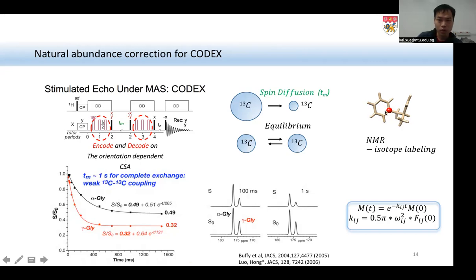In terms of sample, we selectively isotope enrich. This is a demonstration of phenylalanine. We selectively label only one site in the whole molecule. Experimentally, what we observe would be a spin diffusion time-dependent curve. This curve will have an exponential decay and then reach a plateau. The plateau value will tell you how many spins are actually close to each other.